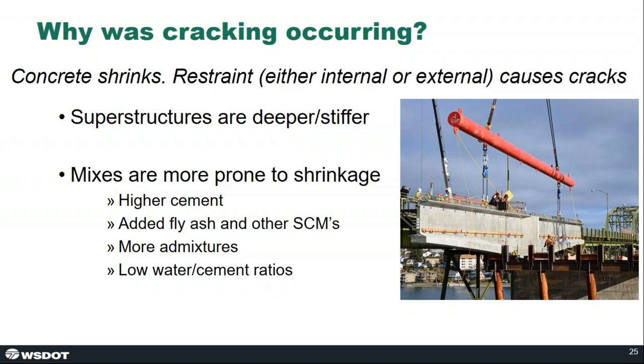And we're seeing lower and lower water to cement ratios. And the lower water to cement ratio is typically a good way to reduce shrinkage. However, when you've got a highly restrained element like a bridge deck, low water to cement ratio can lead to a smaller total shrinkage, but that shrinkage occurs quicker. And the quicker it occurs, the less relief you get from tensile creep. So the earlier you might see tension cracking.